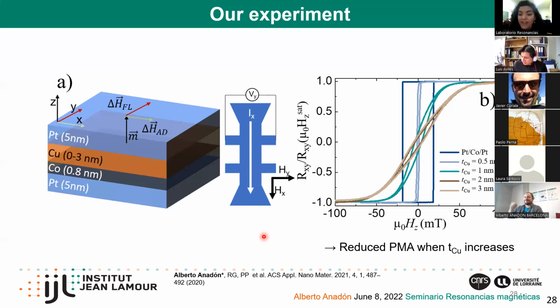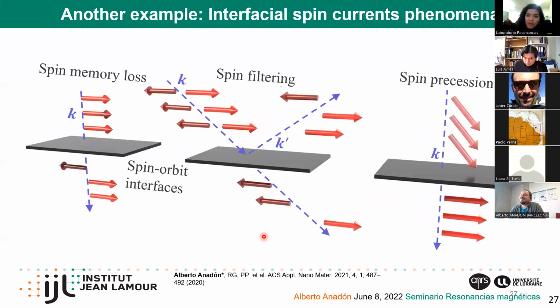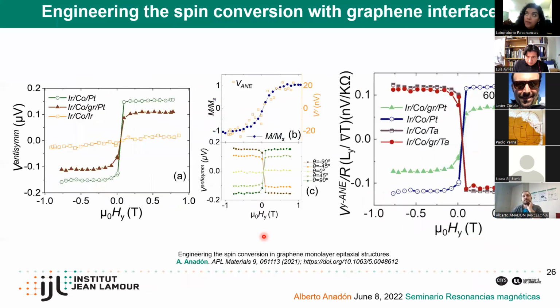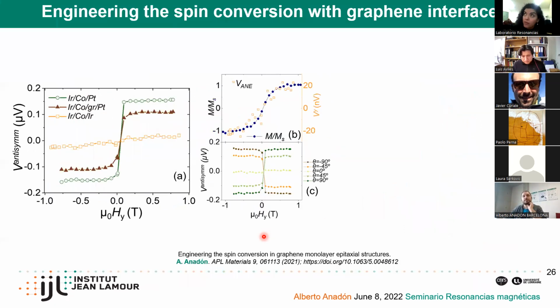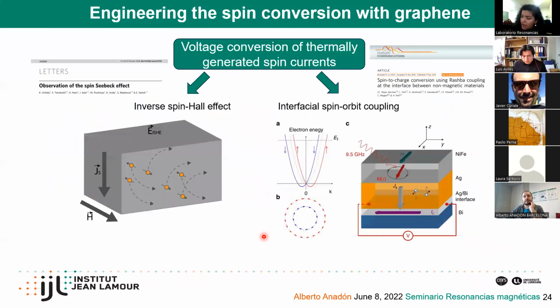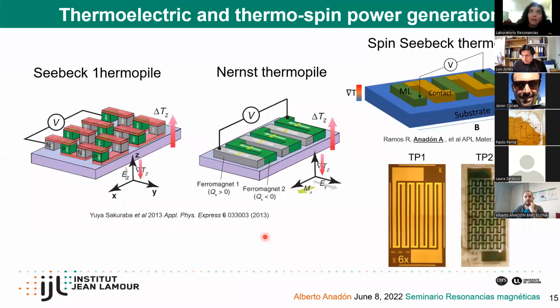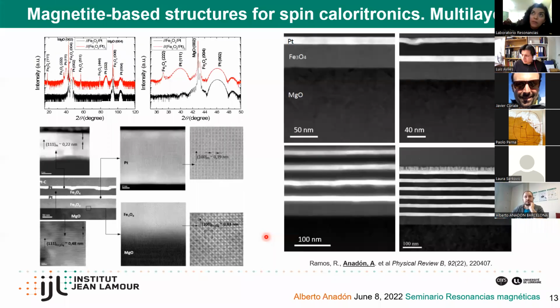I have a question about the first system that you presented, the magnetite over the magnesium oxide, because the magnetite tends to oxidize into maghemite, so the half metallic properties degrade the material. Have you measured how your spin-Seebeck effect changes if the surface is oxidized, and have you evaluated this effect in your samples? Specifically, these ones are perfect magnetite.